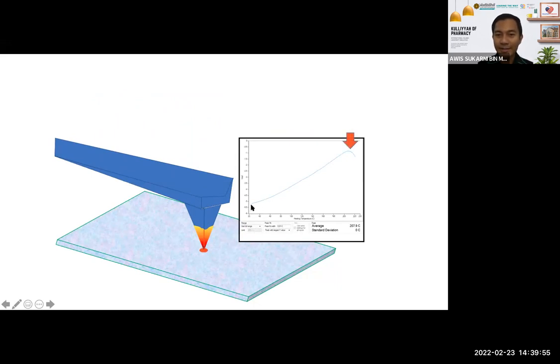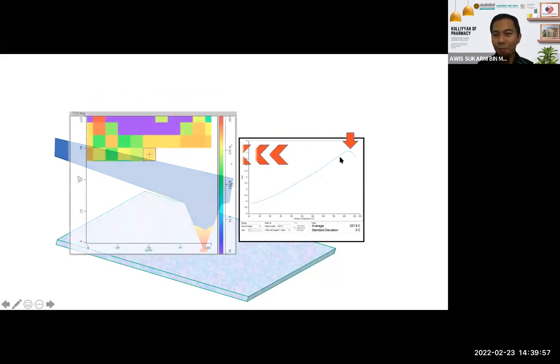And then as you can see here, once they heat up and the surface is softened, it's going to drop. And then they're going to measure the temperature. In this case, the temperature is around 207.9 degrees Celsius. So you're going to repeat the same process at a different point here. Like this one, for example, is 100 micrometer times 100 micrometer, a 100 micrometer square area of the sample.